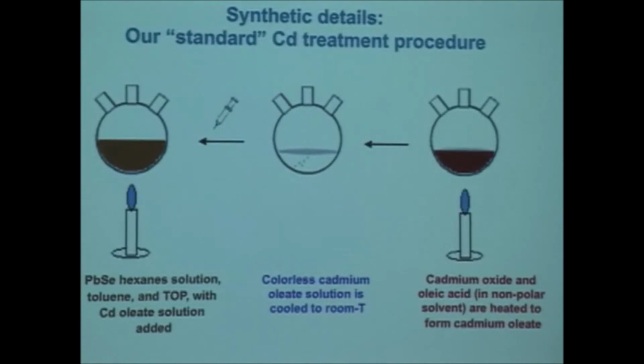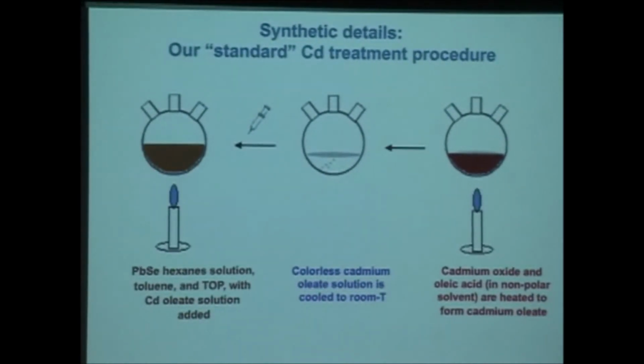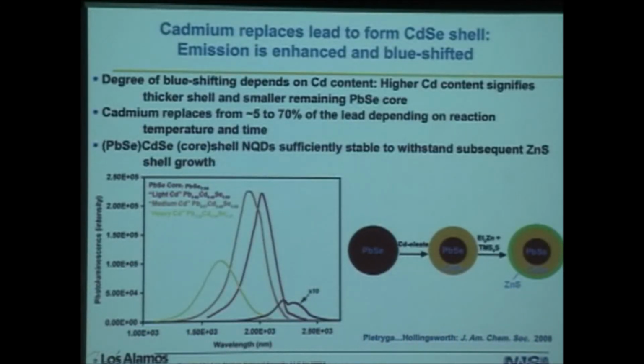Essentially, we introduced cadmium ions to a solution of the lead selenide under controlled conditions, and this resulted in some of the cadmium replacing some of the near-surface lead ions. We were actually able to replace between 5 to 70% of the lead with cadmium. The selenium stays, so you extrude lead and put in cadmium, and effectively shrink the lead selenide core and replace it with a cadmium selenide shell. Once you do this, these particles become more like cadmium selenide than lead selenide, and you can grow, by standard methods, other shells on top of that, like zinc sulfide, and make them nominally more biocompatible.